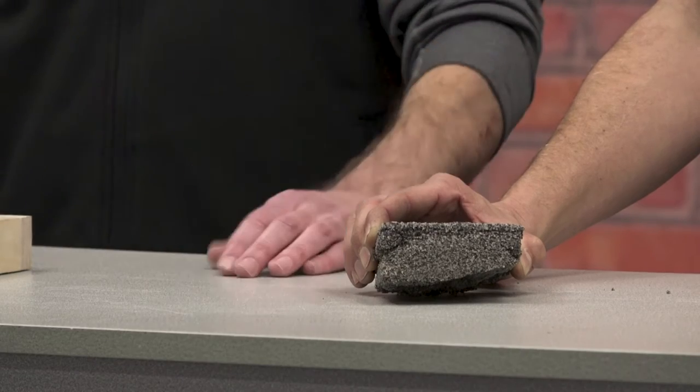Polymeric sands, they don't harden all the way through, top to bottom? No, they're not going to. And so when we talk about some other products, like our Nitro Sand, that's one of the advantages. And again, it's going to depend on the project. The right product for the right project is the other thing that we really want to drive home. But you're not going to get a totally set up joint with polymeric sand. What we're shooting for is, if we have it below the chamfer so that the water can channel in there and we're applying enough water, which is key, you're going to get a nice inch and a half thick crust.